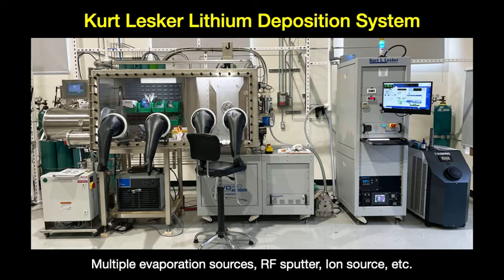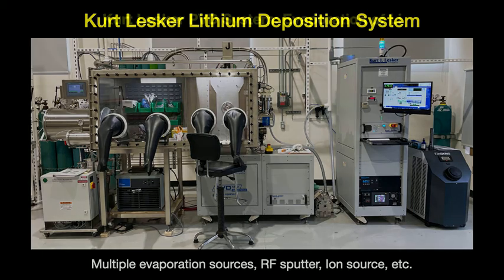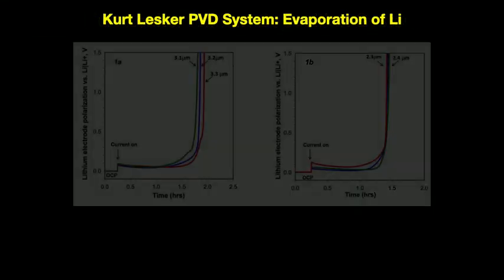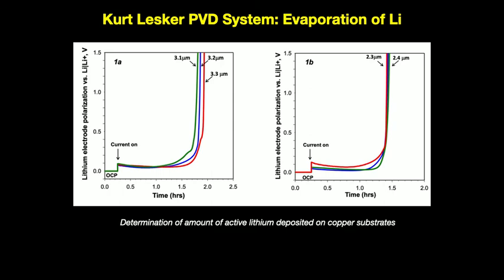So here you see the PVD system we have. We can evaporate lithium onto our sulfide glass. And one of the things we do when we're calibrating the system is simply to evaporate lithium onto copper substrates and then strip the lithium off the copper to see how reproducible this evaporation step is. And you can see here it's quite reproducible. Depending on the time and temperature that you're evaporating at, we get very good reproducibility. This is several microns of lithium on the left and a couple of microns of lithium on the right. And we electrochemically strip it to ensure that we have the lithium we think we have there.